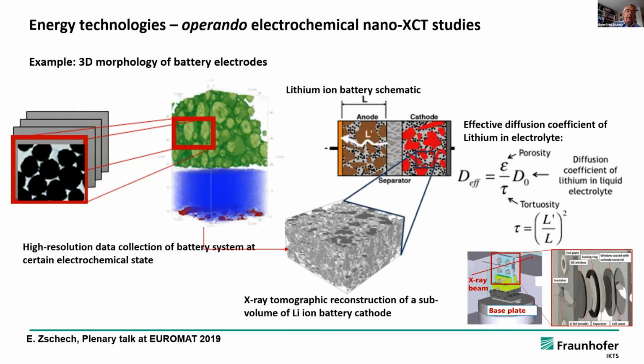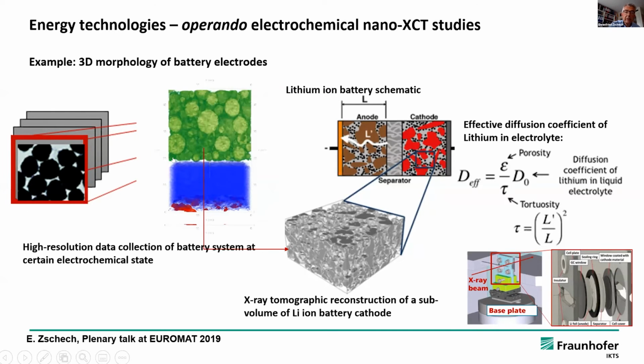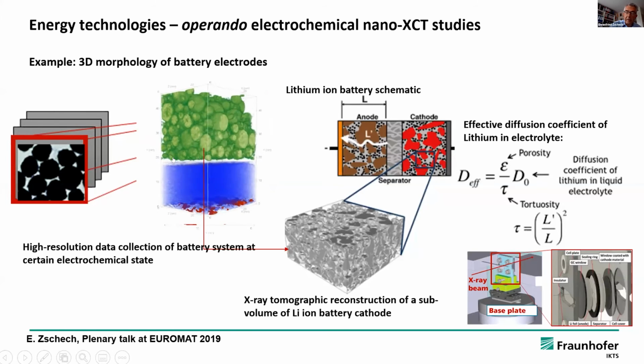The third example that I would like to show is from energy technologies. Electrodes for batteries have a high open volume. These are porous materials. And from X-ray tomography, it is possible to determine parameters like porosity or parameters that characterize the interconnectivity of pores, like tortuosity. And these parameters can be used, if we determine them experimentally, for fluid dynamic modeling to improve the morphology of battery electrodes. And here you can see how such a nanotomography looks like.